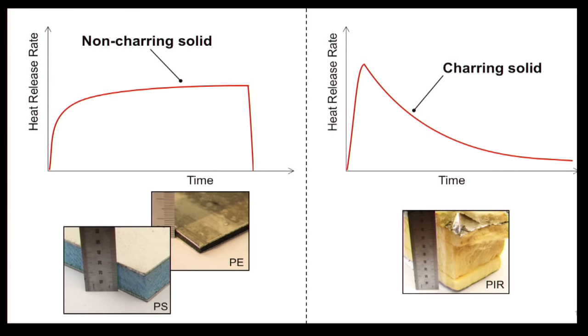A material's thermal inertia relates to how quickly its surface will increase in temperature when exposed to heating. This has consequences for ignition and surface spread of flame in particular. Materials with a very low thermal inertia, such as PIR foam insulation, are likely to spread flame rapidly, particularly when their external surfaces are not protected by a metal facing. Thermosetting polymers like PIR will char on heating, whereas thermoplastics like polyethylene and polystyrene will melt. This again has important consequences for the extent to which the total energy available is actually released during a fire. And I've illustrated that again here with respect to the non-charring and charring behavior of various polymer solids.